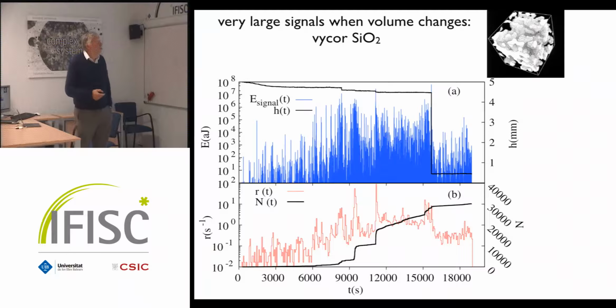Okay? So we squeeze this one, and then one pore will collapse. It's linked to the next pore, which will perhaps also collapse. And then there's another one which might collapse, depending on the coupling. And then there's one, because it's a non-local phenomenon, at the edge of the sample, which then, by sympathy, also collapses. And you have these networks, these collapse networks. And then each time there's a collective collapse, the collective thing is the avalanche.